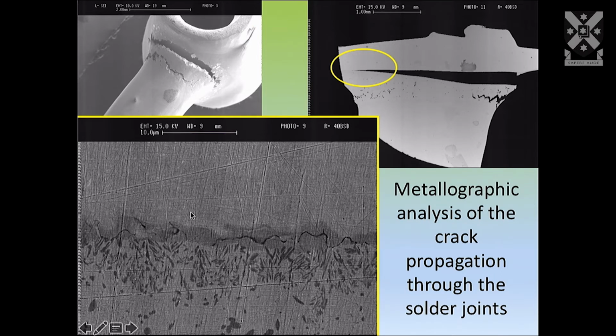What was interesting was that this gray zone here has got the crack in it. So what we found was the cracks were initiating in the solder, often through corrosion, but once they reached the cylinder, it would be a rapid propagation down through this gray zone. And the question was, what is it about this zone that is causing the crack to, in a catastrophic way, propagate down?